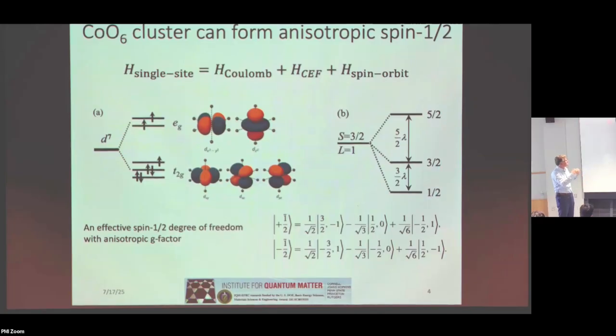So it becomes a Kramer's doublet ground state, and it has all the character of a spin 1/2 degree of freedom, but when I flip the spin or rotate it, I'm actually doing stuff to the orbital sector as well. There's a spin-orbit coupling that ties together the spin and orbital degrees of freedom, and therefore we can expect that the spin actually knows about what the lattice looks like, and so I can expect that I may be able to get a very anisotropic interaction coming in. But that's just the local physics, cobalt with its 6 ligands around it.